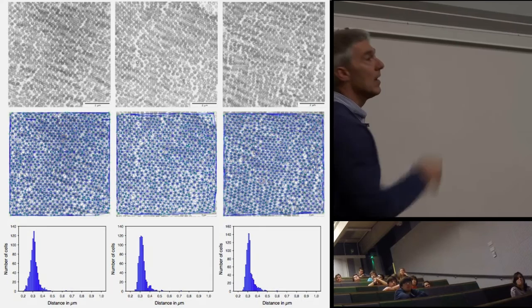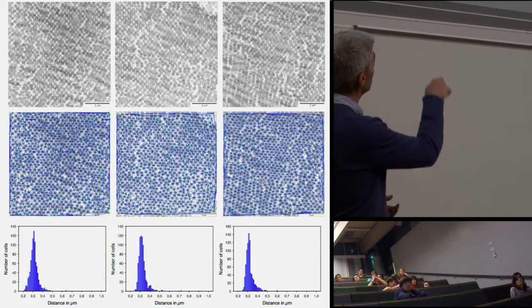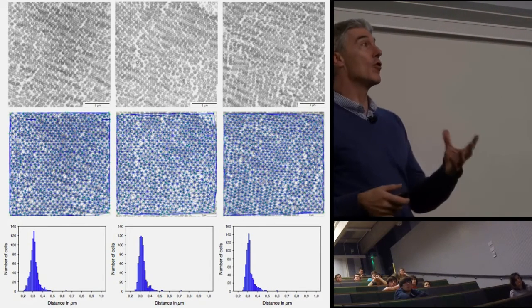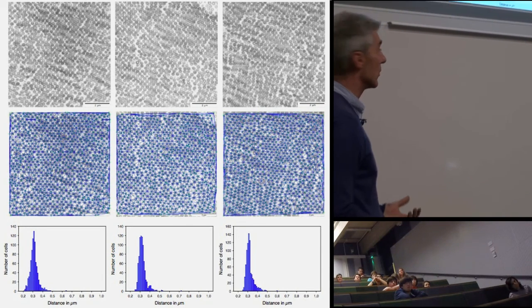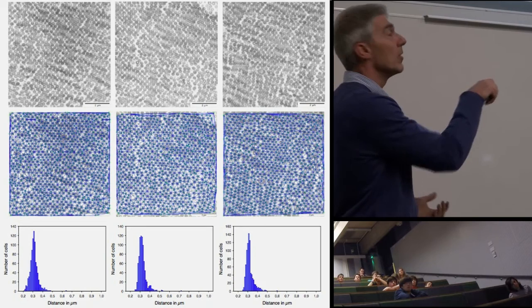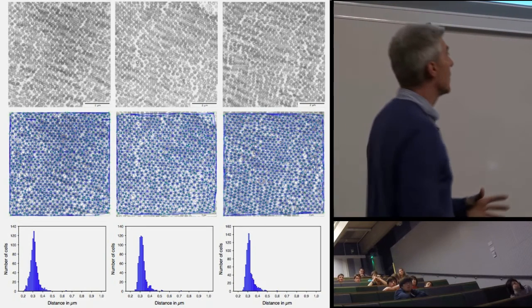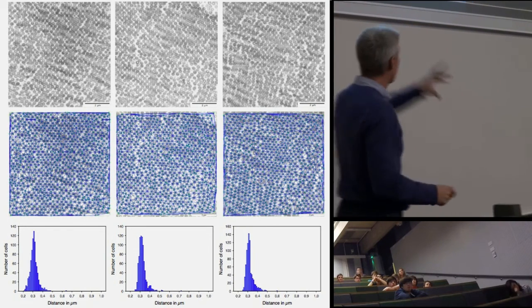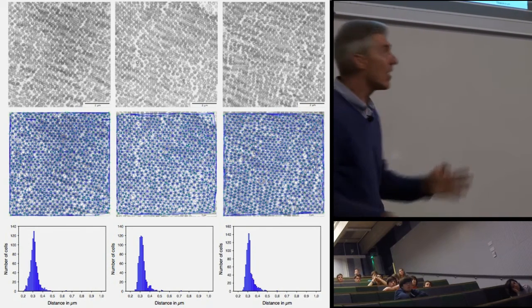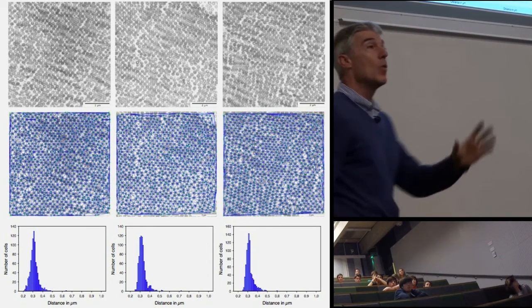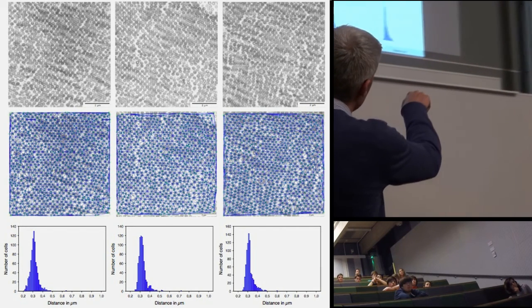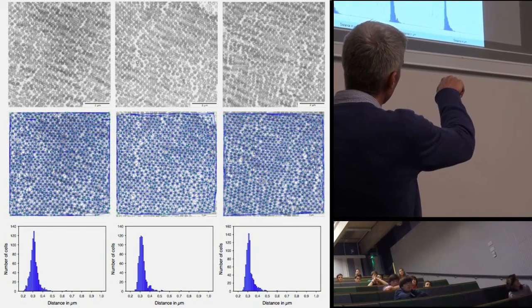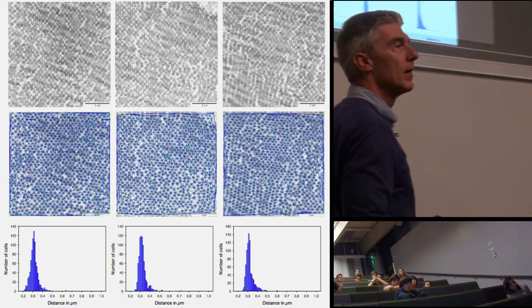Now, these 3 are more ordered systems. Let's throw the grid at them. This is a Voronoi analysis, if you're interested. And now let's plot the distributions. These are much more tight. And even though they're not disordered, they're not really wide, they're not perfectly ordered either, are they? Because they have a width. What we're going to call that is a full width half maximum, let's say. I'm going to say that this right here is of the order of 100 nanometers.